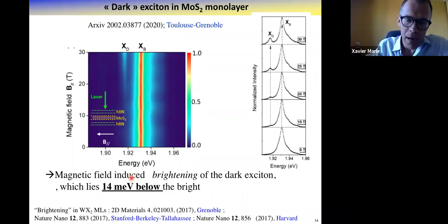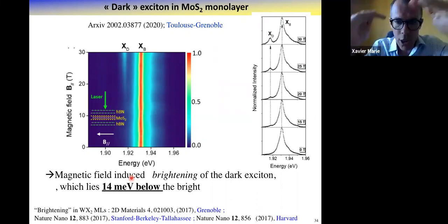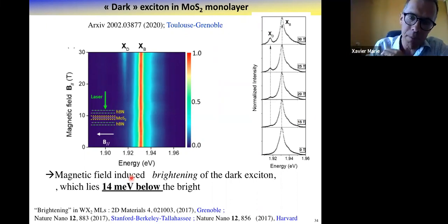Probably, my feeling is that we are close to degenerate spin-up and spin-down states in the conduction band, 2, 3, 4 millielectron volts. And then the 14 millielectron volts has the effect of both exchange energy and the difference of binding energy.